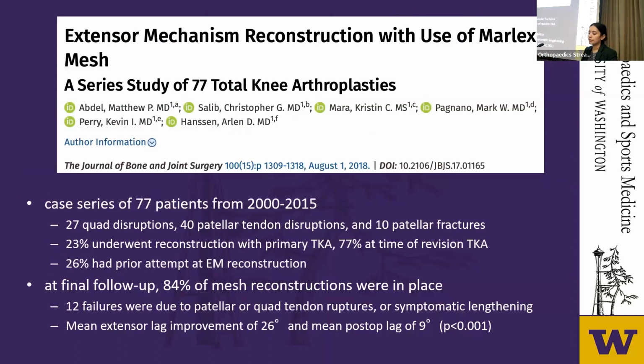So this study is the largest series that was published of patients with extensor mechanism disruptions after a total knee arthroplasty treated with Marlex mesh, and is published by these authors out of the Mayo Clinic in 2018 in JBJS. And there were 77 patients with a mean follow-up of 4 years. And 23% of the patients underwent reconstruction for a primary TKA, while the rest underwent it during revision TKA. And of note, 26% of them had a prior attempt at reconstruction. And at final follow-up, 84% of the mesh reconstructions were in place. There were 12 failures due to patellar or quad tendon ruptures or symptomatic lengthening, but the mean extensor lag improvement was 26 degrees and the mean post-op extensor lag was 9 degrees.